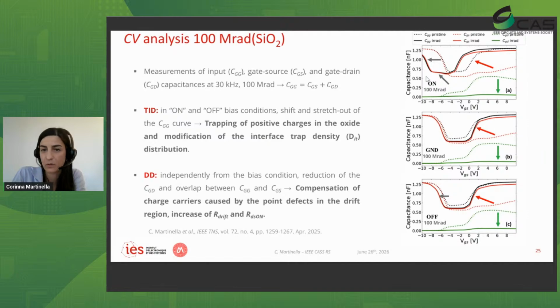For example, if we look at the one in on-state, we have a combination of TID and displacement damage. If we look at the input capacitance in black, we have the pristine one in dotted line here. We can see that there was a shift towards the left, and this was due to the total ionizing dose. Then we also have a stretch of the bottom part, and this is due to the generation of interface defects from the irradiation.